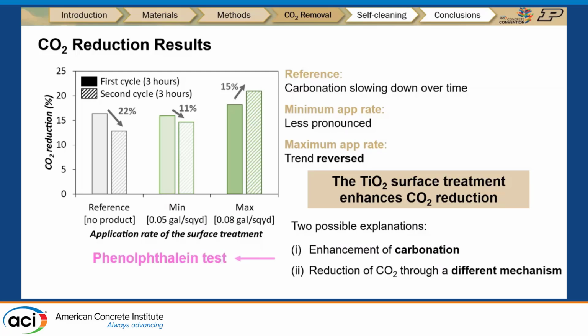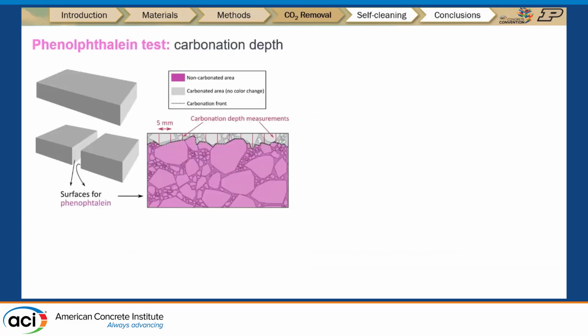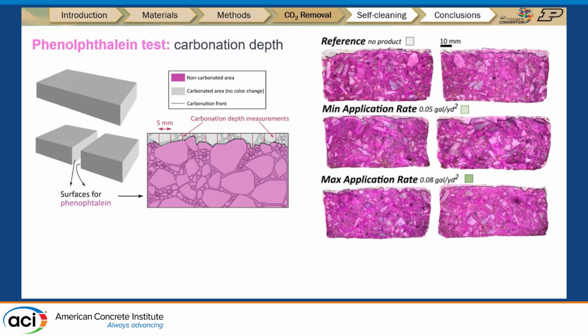So in order to know that, we did a phenolphthalein test. The phenolphthalein test is a test that we use to measure the carbonation depth. We spray the phenolphthalein, which is a pH indicator, on the freshly cut concrete sections, and we measure the carbonation depth at intervals of 5 millimeters. On the right-hand side, you can see our images for the phenolphthalein test, and you can barely see a difference in all 6 samples. In fact, the carbonation depth is not really affected by the surface treatment.